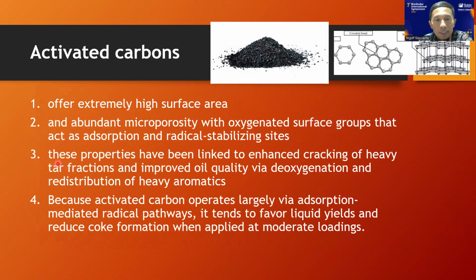Third, these properties have been linked to enhanced cracking of the heavy tar fraction and improved oil quality via deoxygenation and redistribution of heavy aromatics. Because activated carbon operates largely via an adsorption-mediated radical pathway, it tends to favor liquid yield and reduce coke formation when applied at moderate loading. These are some special characteristics of activated carbon that support catalytic activity.